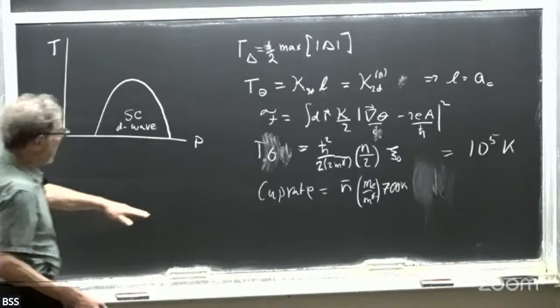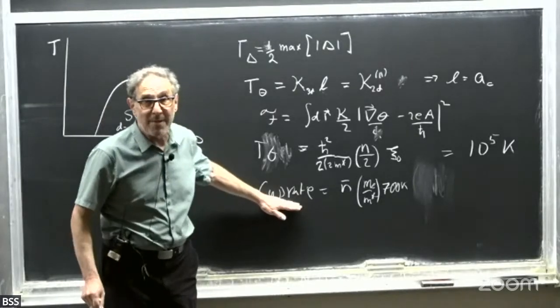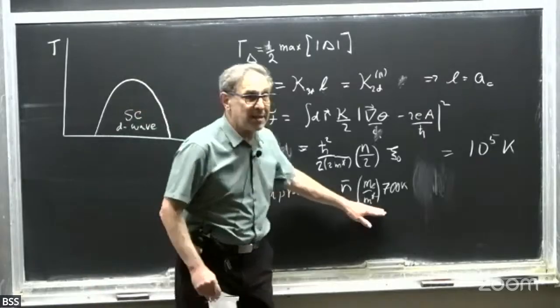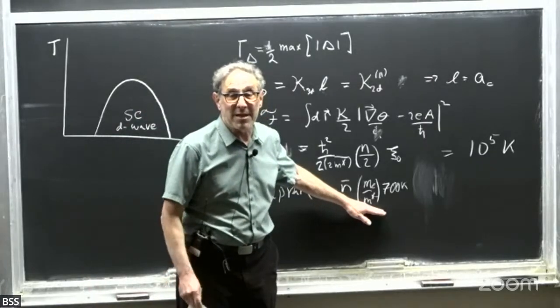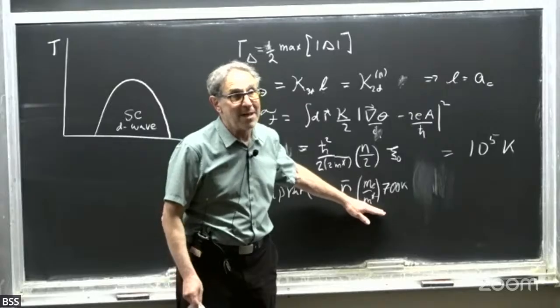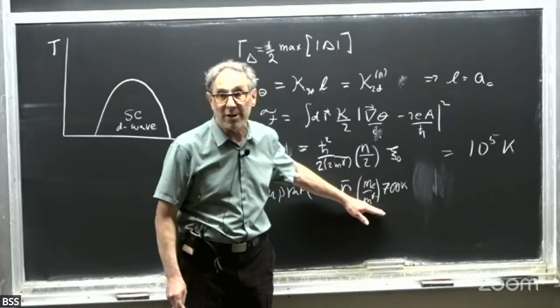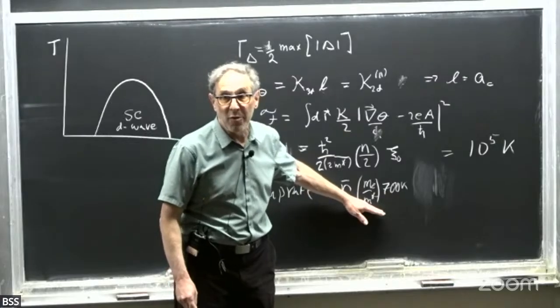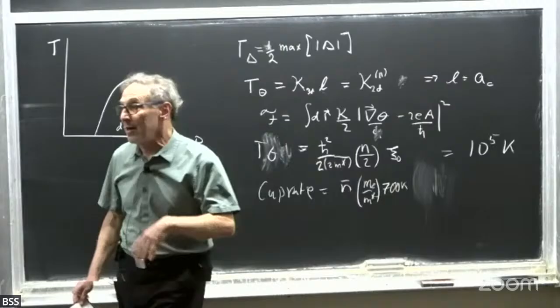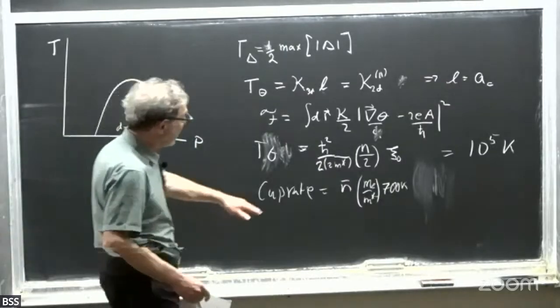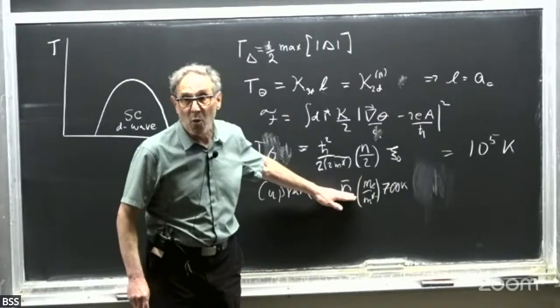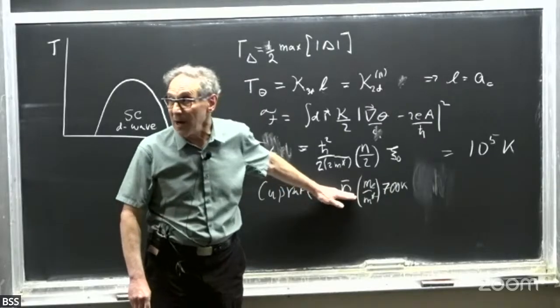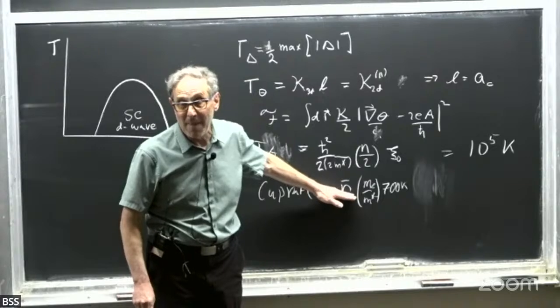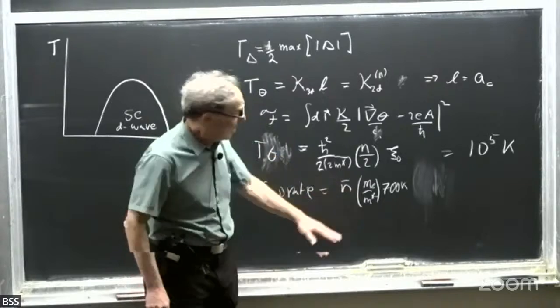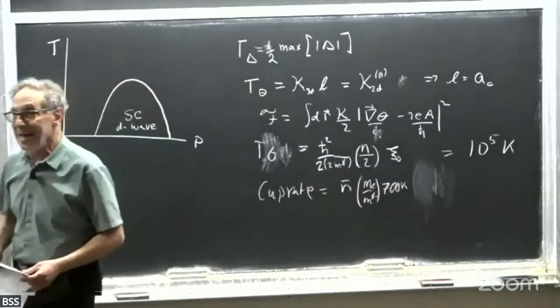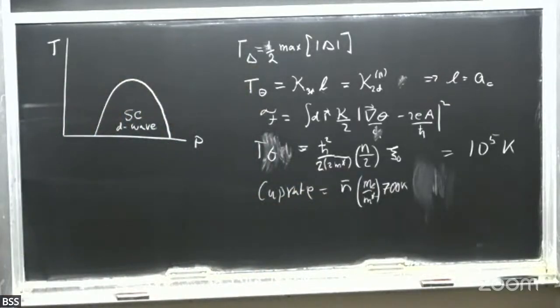There are all sorts of things that may change this estimate by making it smaller. For instance, many say masses are like 2 or 3 electron masses rather than like 1. That would reduce this estimate by a factor of 2 or 3. There's also a question about whether I should be looking at 1 plus p or p electrons per copper. That could also make up to an order of magnitude difference in this estimate. So this is sort of the biggest number I can get for T theta, and it's already in the ballpark of Tc. Yeah.